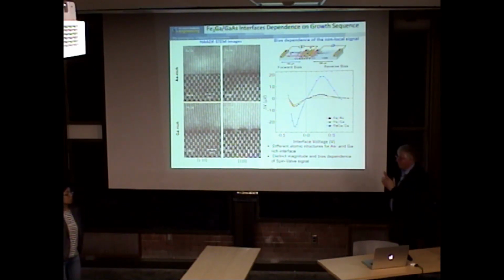We've just done some work, not for cobalt 2 manganese silicon, but trying it with cobalt 2 manganese aluminum and iron 2 manganese aluminum. It's not a 100% spin-polarized material, but there's some theory that if you do a superlattice, it's supposed to be, and we were trying to see if it was. We just came back from France a week ago, so the data is a little new to see. Any more questions?